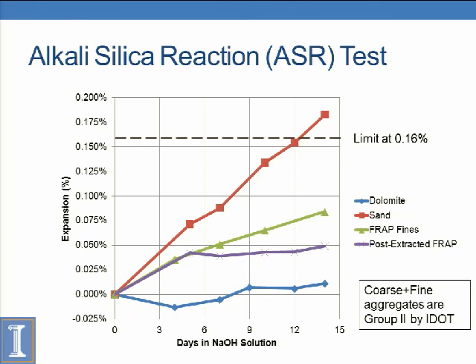So testing our aggregates, we see that our dolomite, which is our virgin coarse aggregate, was pretty much non-reactive, just 0% expansion with time. You make these mortar bars and store them in sodium hydroxide solution, so you're constantly supplying alkalis for this reaction. And so we can see that dolomite was non-reactive. This was the FRAP, which we tested after we removed the binder, and that was also a dolomite aggregate, so non-reactive. The FRAP fines themselves expanded a little bit more, probably just from the asphalt swelling.